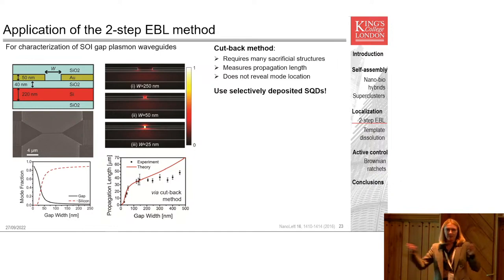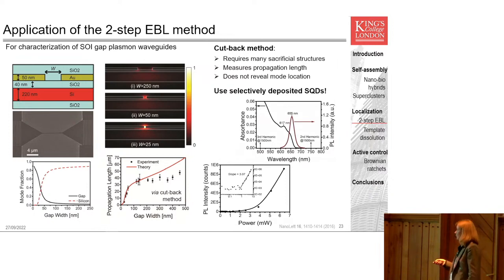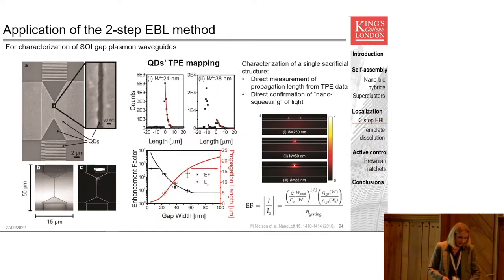So essentially, the coupling efficiency at different cut-back lengths. However, it's much easier to just use selectively deposited quantum dots on a single structure to do the same thing. In this case, we use the 3-photon emission from the quantum dots, with the idea being that we pump in the waveguides at 1500 nanometers. And so our third harmonic of that occurs at 500 nanometers, where the quantum dots absorb strongly, and then they emit at 650 nanometers, where there's no other signals in our system, so we can very easily measure our fluorescence from the substrate.